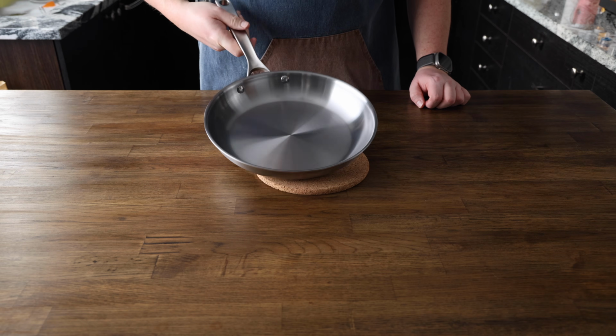Preheat your oven to 450 degrees Fahrenheit or 232 degrees Celsius. You want to make sure you have it a little bit higher than the smoke point of the oil, about 25 degrees, because sometimes ovens don't hit the temperature they say, and you want to make sure the oil is getting polymerized to the carbon steel. Then place it into the oven upside down on the middle rack. This positioning helps prevent the oil from pooling on the surface of the pan.